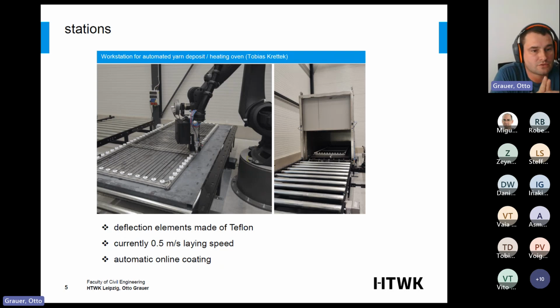Once the reinforcement has been completely deposited, the clamping frame together with the reinforcement is fed to the thermal post-treatment. For this purpose, it moves independently within the model factory to the next process step. In a circulating air oven, the scrim is subjected to a thermal post-treatment regime or tempering specific to the resin. Here we use an epoxy this time, but it's also possible to use other resin systems.